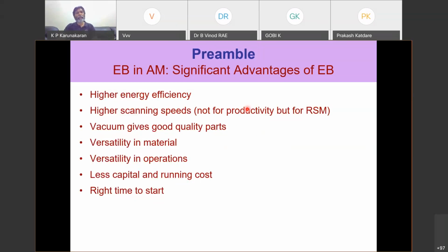Now coming to electron beam in additive manufacturing, the most important advantage, when we talk to people connected with energy or government agencies, we can say that energy efficiency is high because a laser is hardly 15 to 20% energy efficient. We are talking about energy drawn from the wall plug as electric energy. That is on the denominator, and put on the numerator the heat it actually creates. That is hardly 15 to 20%. Sometimes people claim 40%, 45%, but they are all under very ideal conditions. But average is never more than 15 or 20%.